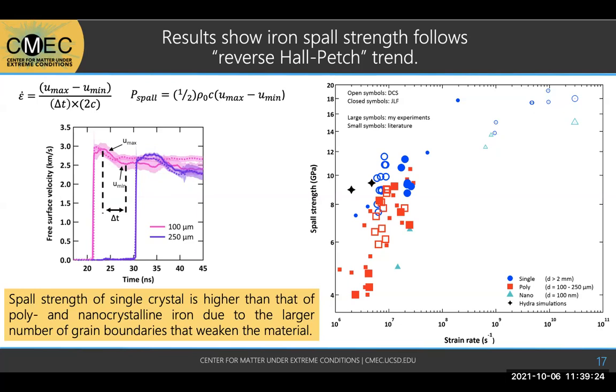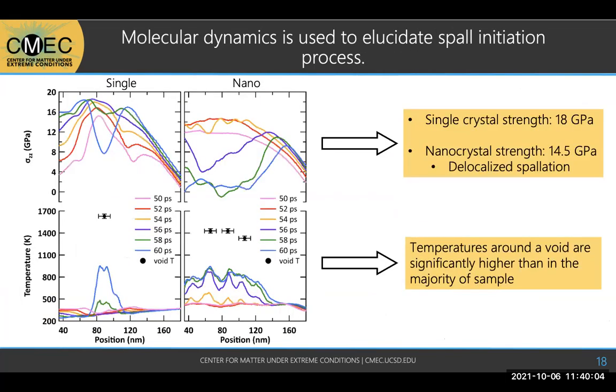And it all kind of agrees. There's obviously some differences, especially in the polycrystalline in the red, but that's a whole other explanation. But in general, we see this reverse Hall-Petch trend where single crystal iron is stronger than nanocrystalline iron because of the presence of grain boundaries, which weaken the material. I call this reverse Hall-Petch because a normal Hall-Petch relationship means smaller grained is stronger, whereas here it's weaker because it's a failure process. Next slide.